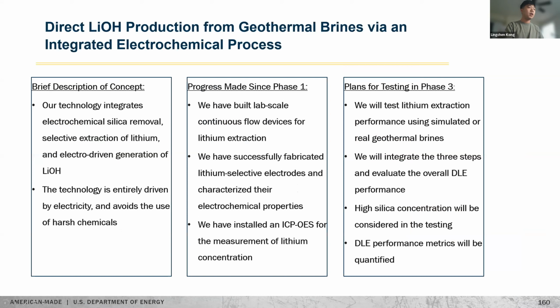Next slide, please. Our proposed technology consists of 3 steps: electrochemical silica removal, selective lithium extraction, and then the electro-driven generation of lithium hydroxide. During phase 1 and phase 2, we already built a continuous flow device for lithium extraction, and we successfully fabricated the lithium selective electrode and characterized its electrochemical performance. We also talked with our IAP member and tried to optimize the design. For the next phase, we will test the performance in a real geothermal brine, and we will also integrate all 3 steps together and evaluate the overall direct lithium extraction performance. We'll also consider the high silica concentration in the next step.